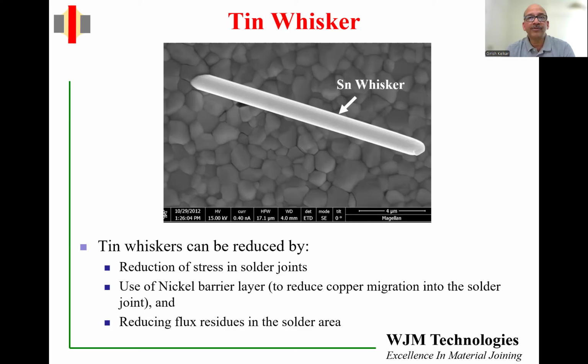However, now that we are using lead-free solders, we have to deal with this phenomenon called tin whisker. So what exactly is a tin whisker? I'm showing you a photograph over here where a tin whisker has grown. It's like a single crystal. It's almost like a needle. It grows from the solder surface. And if it grows in the direction of a neighboring electronic component, it's going to create a short and the device is rendered useless.